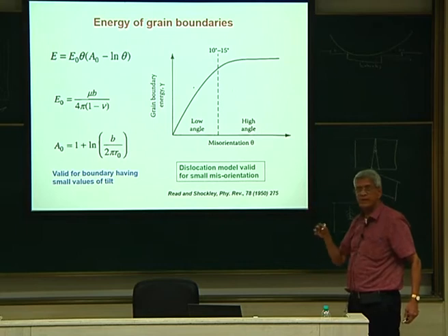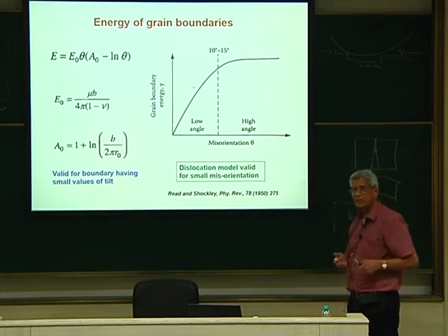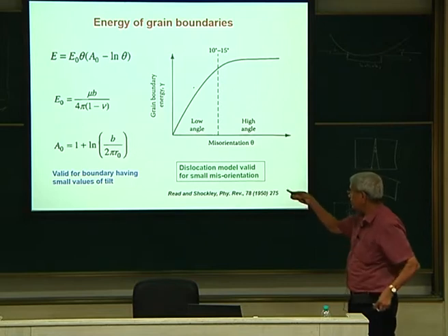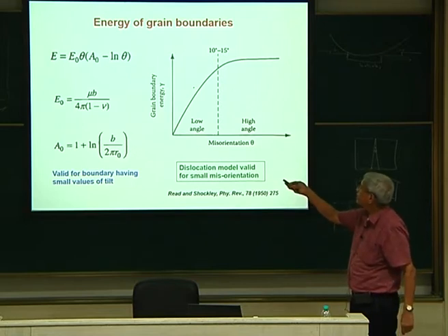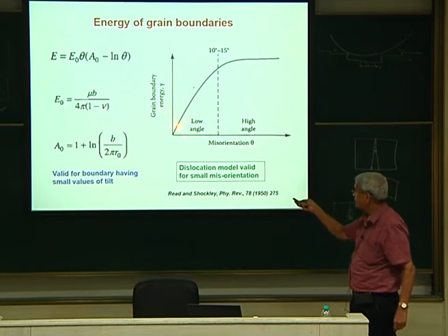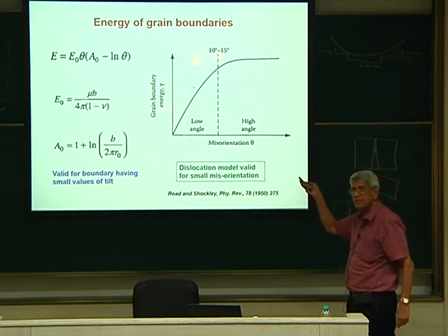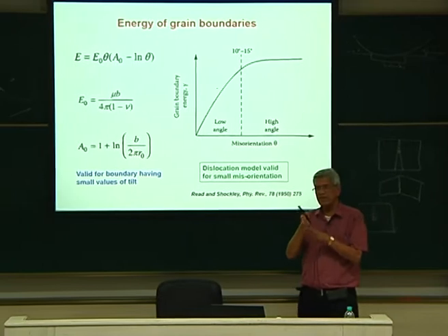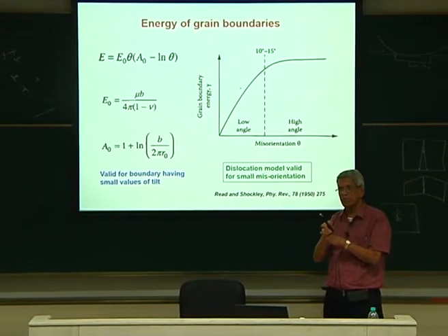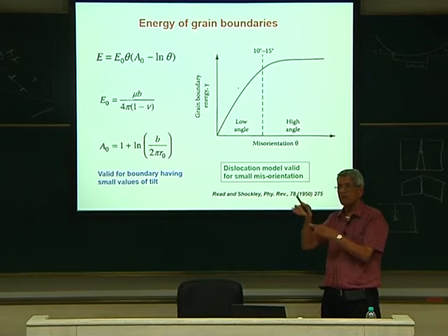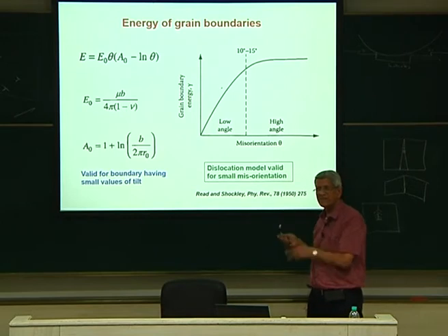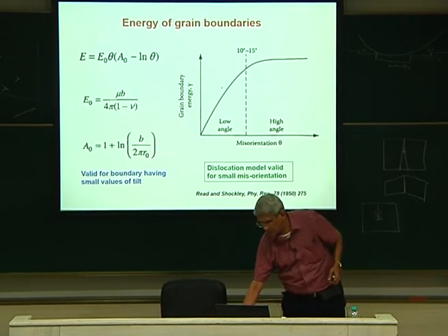And if we increase the dislocation density on that plane, the boundary angle or the misorientation is going to increase, correct. So, this is given in detail. With respect to the misorientation, the boundary angle increases. It does not increase infinitely, because when we consider the tilt of about 10 to 15 degrees, essentially that is the time when the core of the dislocations merge. Then we can't say that we are seeing a dislocation there. The distinct dislocations could be seen only when the angle is less than 10 degrees. Okay. All these aspects you have studied.